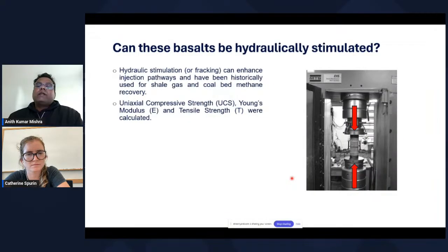Well, we can hydraulically stimulate these basalts. And for hydraulic stimulation, we can test these core samples with different geomechanical tests. So this is what we call the setup for uniaxial compressive stress, where we put the basalt core samples and apply pressure. With this test, we can estimate the uniaxial compressive strength, the Young's modulus, and the tensile strength. For tensile strength, the setup is a little bit different, which I have not put in here.